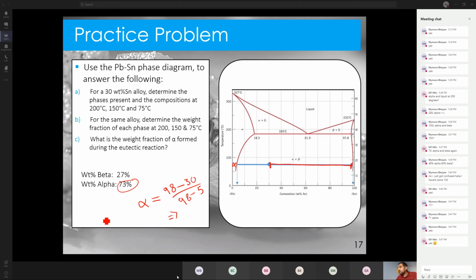That one is really easy. What is the alpha made of? All you need to do is just draw a line and read the value. So it looks like the alpha is 95% lead and 5% tin. So alpha is not pure lead, but it's almost. The beta is 98% tin and only 2% lead. So very high tin concentration in the beta.